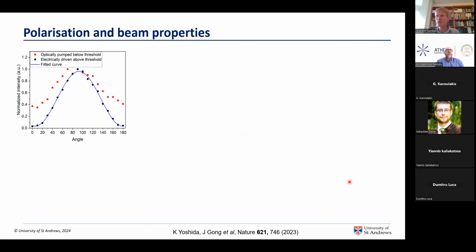So we've also characterized the output beam from this laser device, and this shows the intensity through a polarizer as you rotate the polarizer analyzer angle. As we rotate the polarizer from 0 degrees to 90, we have a very high polarization ratio of the emission above threshold. It's still polarized light below threshold, but that's characteristic of the grating structure and the waveguide, but it becomes much more strongly polarized when you go above threshold.